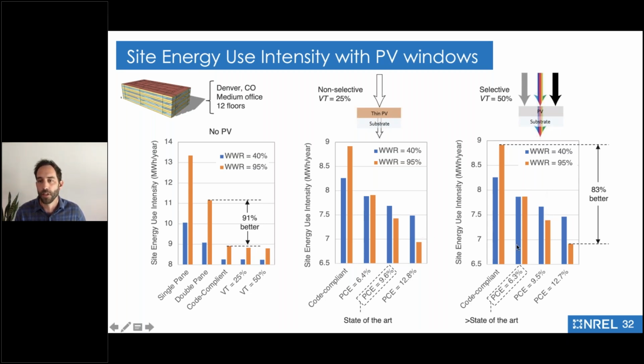And if you look over here at the selective glazing, so this would be, say, generation 3, or these organic photovoltaics, or the wavelength selective photovoltaics. Again, site energy use on the left axis, the code compliance or the low E glazed window on the left side. And then on the next 3 bar graphs, we have different power conversion efficiencies. So the major difference here is that you can get similar power conversion efficiencies out of both technologies, but the VT, or the visible transmittance, of the non-selective absorber has to be about 25% to get the same power conversion efficiency, whereas in these organic photovoltaics, or these selective wavelength absorbers, you can get to about 50% VT, and this is just the outer light, the VT. You get to about 50% and get the same sort of power conversion efficiency.